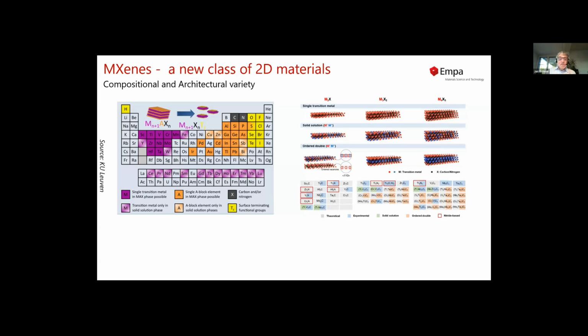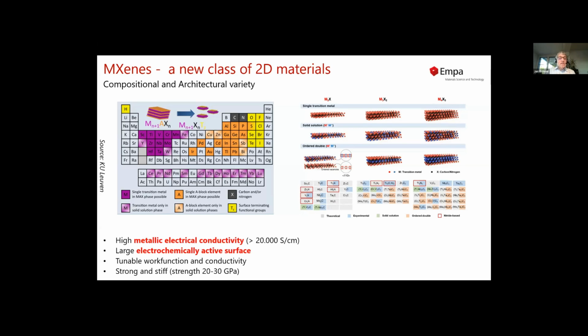MXene layers. They mainly stick out for metallic electrical conductivity based on the transition metals. What makes them very interesting for sensing and also energy storage applications is a very high electrochemically active surface. Via composition, you can tune the work function and the conductivity. The materials are also very strong as 2D materials. And most importantly for our field, they are easily processed from their colloidal suspension, so they are exfoliated in solution, and you can make inks from them.